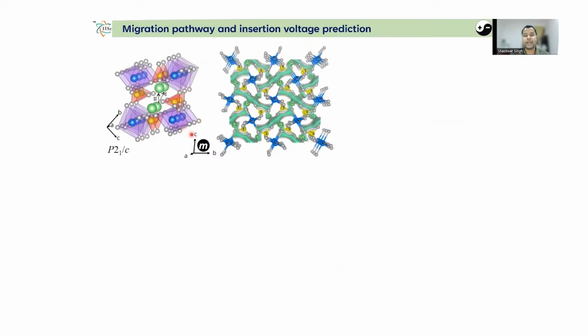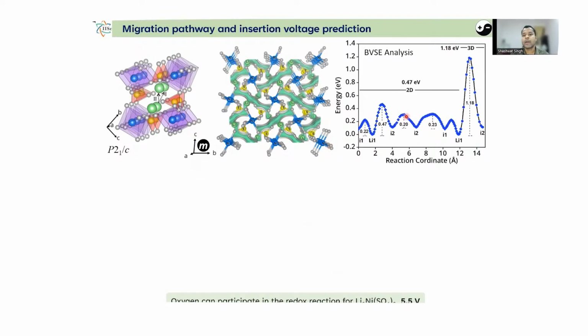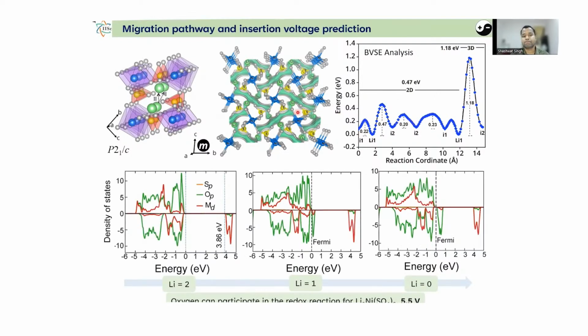This lithium nickel bisulfate compound basically offers a two-dimensional pathway for lithium ion migration as calculated from the bond valence site energy calculations. And the migration barrier would be 0.47 electron volt. However, more precise values can be obtained through rigorous DFT-based calculations. Now, since nickel is known to offer a very high redox potential, whatever attempts we made to study the electrochemistry were a failure, and therefore we took help of DFT-based calculations to look at the voltage and what mechanism will be involved.